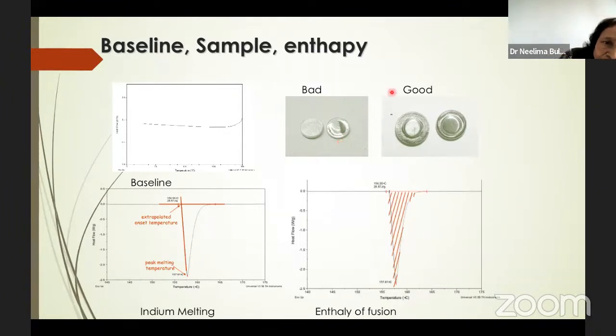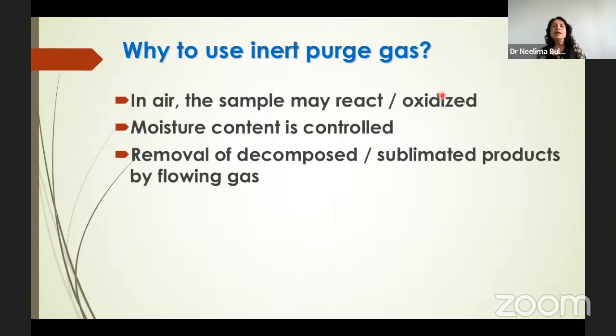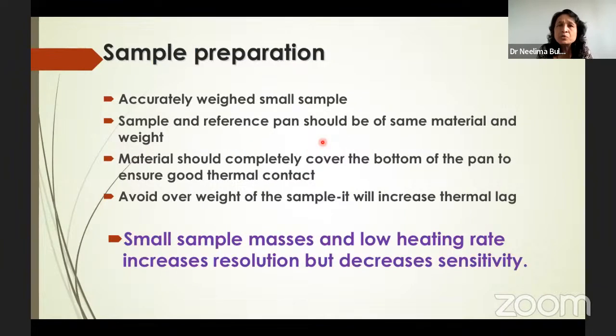Yeah. So this is a bad and this is a good sample pan. Now, DSC is usually done in an inert atmosphere like nitrogen, because in air, the sample may react or oxidize. Then moisture content can be controlled if you use an inert atmosphere. So it's always advisable to use DSC in an inert atmosphere. And I think I have told you to accurately weigh the sample pan and sample material, and avoid excess weight.